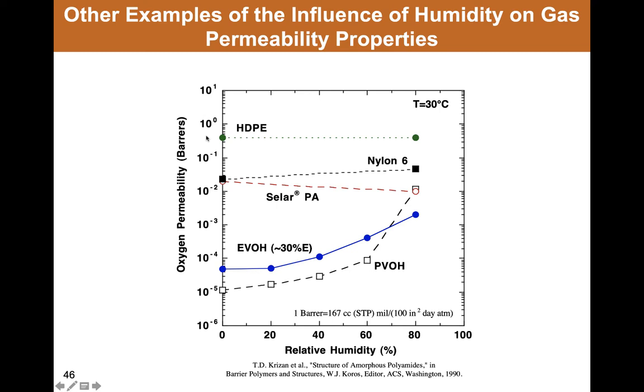Another example of the impact of humidity on gas permeation properties is shown here. This is a plot from the barrier packaging literature, so food packaging literature. Essentially it shows that in very nonpolar materials like high density polyethylene that sorb almost no water, the impact of humidity on the permeability of other gases is negligible. In Selar, the permeability of oxygen actually goes down as relative humidity goes up. This is because of these dual mode sorption effects. And in polyvinyl alcohol and a copolymer of ethylene vinyl alcohol, which has about 30% ethylene in it, and the balance is vinyl alcohol, the oxygen permeability goes up dramatically as relative humidity goes up.